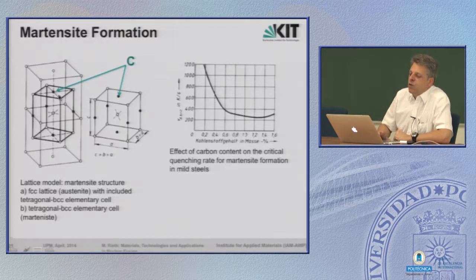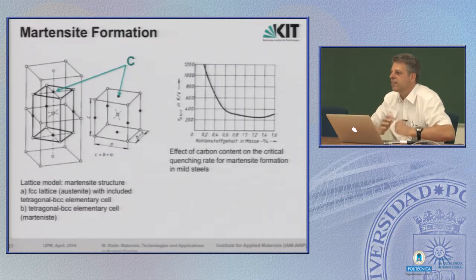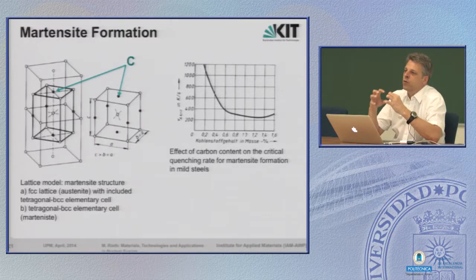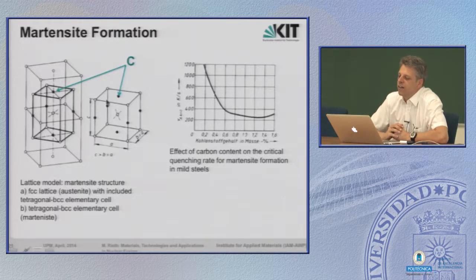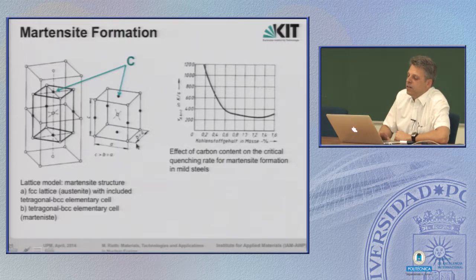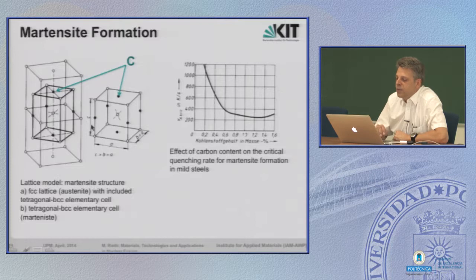And if you cool down with a high enough speed, as we have seen, then an easy explanation is the quenching is so fast that the carbon atoms have no time to diffuse to some other place. They are captured within the iron lattice. And as a result, we end up not in a BCC, not in a FCC structured lattice, we end up in a tetragonally distorted BCC structure.